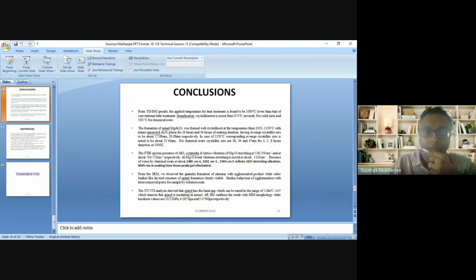So in conclusion, we can say that we are getting the spinelization at a much lower temperature, below 1000 degrees, in contrast to the crude solid state process, which is around 1200. We are getting it for modified solid state at 870, and for the chemical route close to 500 initiation. And obviously phase formation takes more duration for the solid state process, around 26 hours and 36 hours, while in the case of the chemical route the heat treatment durations are just 4, 5, 6 hours.